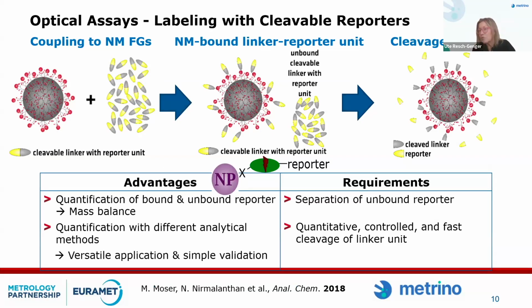Alternatively, you can use a cleavable reporter. Such molecules are also commercially available. They are also used by industry. So here you have the same principle. You have your particle with the functional groups reacting with your probe. Then you cleave your probe and measure the probe in solution after removal of the particle, so you don't have problems with scattering or absorption from the particle, and quantify your reporter.